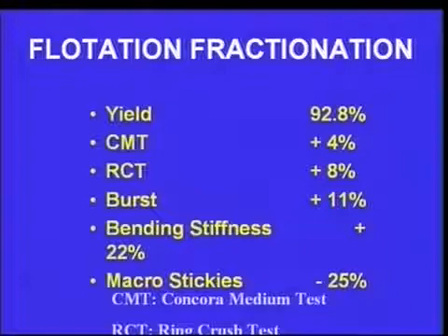Here is an example of froth flotation used in fractionation. Your yield can be 90 to 93%, and corresponding increase in the compressive strength of the paper, tensile and compressive strength of the paper or burst strength of the paper are indicated here. Bending stiffness also increases by 22%, and macro stickies are reduced by 25% because they have been floated out.